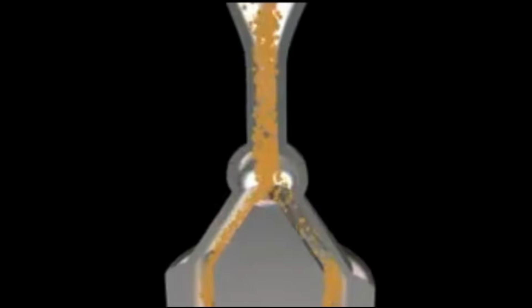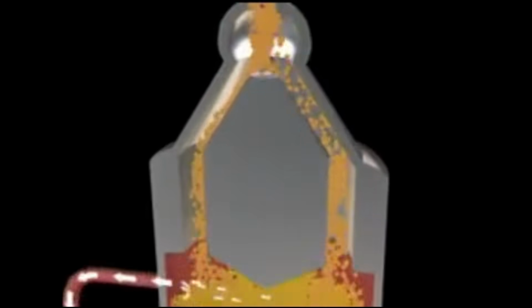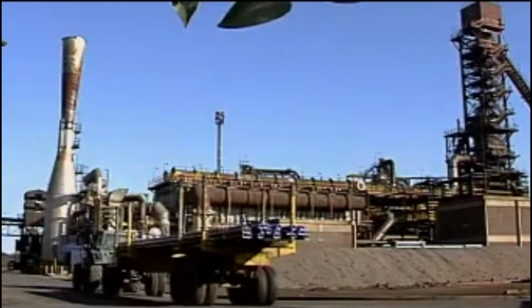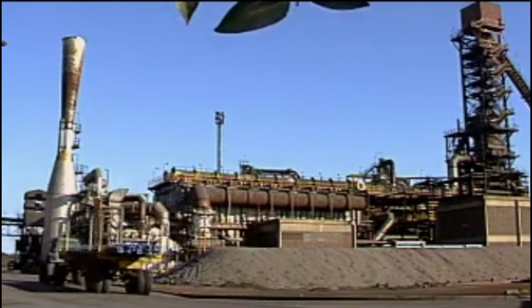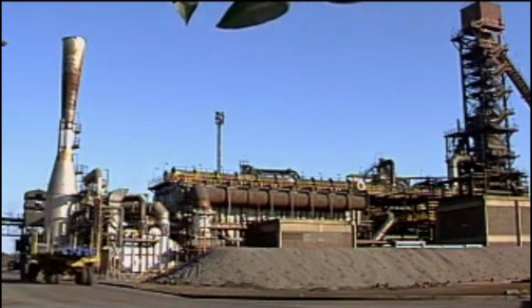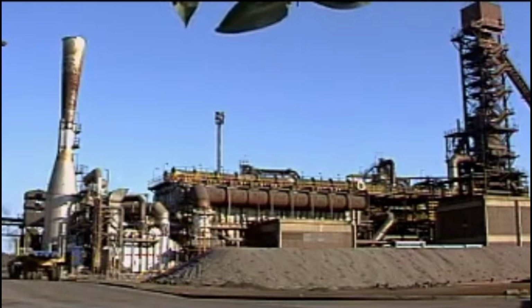During this period, a continuous flow of reducing gases, mainly a mixture of hydrogen and carbon monoxide, is injected. These gases react chemically with the ore, removing its oxygen content and converting it into direct reduced iron, commonly known as sponge iron. The ore enters the furnace at ambient temperature with roughly 67% iron content. Inside the reactor, it is heated to around 960 degrees Celsius. By the time it exits, its metallization degree reaches approximately 95%, before cooling back to room temperature.